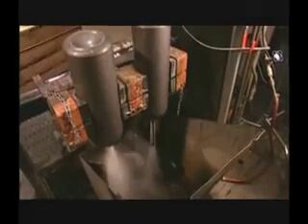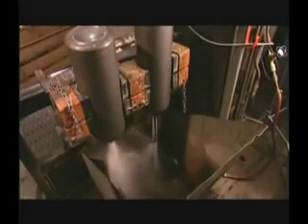Hydrostatic testing is performed using the volumetric expansion method. Prior to performing the test, the internal volume and tare weight is recorded for each individual cylinder. Cylinders are either pressurized to 5/3 of service pressure for DOT 3AA cylinders or to a different specified value for special permit cylinders. Once testing is complete, cylinders are cleaned with hot water and purified air.